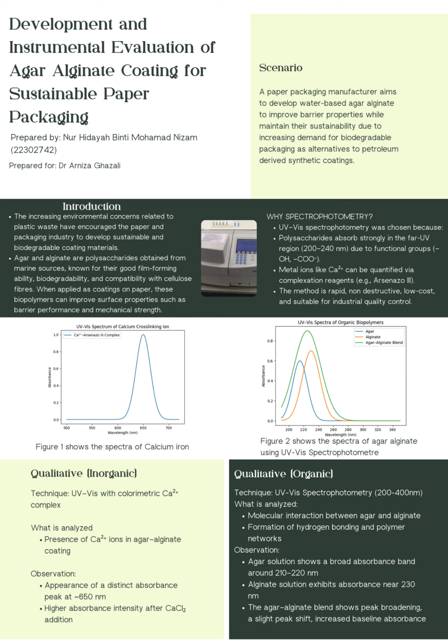between agar and alginate. For qualitative inorganic analysis, the extract sample was reacted with the reagent and scanned from 500 to 720 nanometers. A distinct absorbance peak at approximately 650 nanometers was observed, confirming the presence of calcium ions, which act as cross-linking agents in the coating.